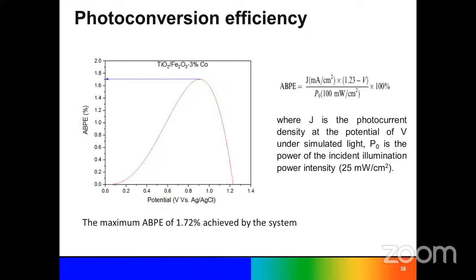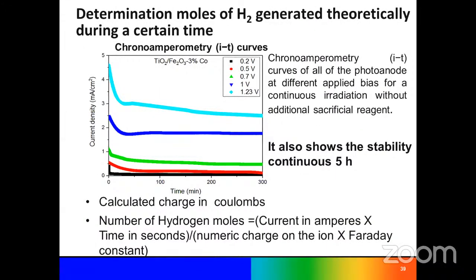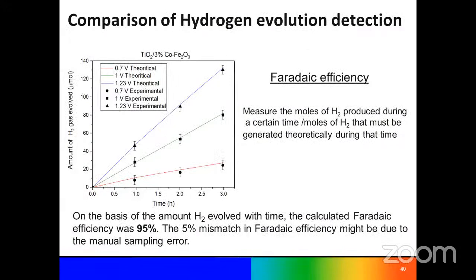but without coating the surface with the photon response materials. For these reasons, just 1.72%. We checked the stability of this material. After 5 hours, the stability of the material still remains the same. There are no changes. So more or less, these materials are stable at around 5 hours. Then we checked the Faradaic efficiency. In the case of the Faradaic efficiency, we got around 95%, with a 5% mismatch due to some sampling error in this case.